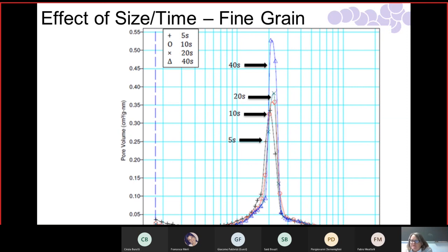If you only want to know where the peak is, you don't have to go as slow. In this particular aerogel, right, the peak is around 22 nanometers. And most of them capture that pretty well. But they won't get the total pore volume. So with aerogel, I am always very careful about reporting on pore volume. If I want to do it, I do very, very slow tests to make sure I capture that peak.